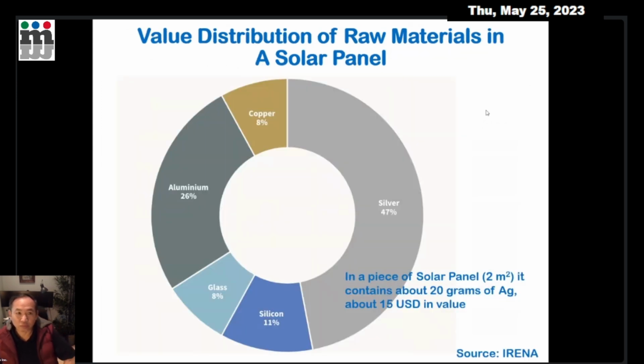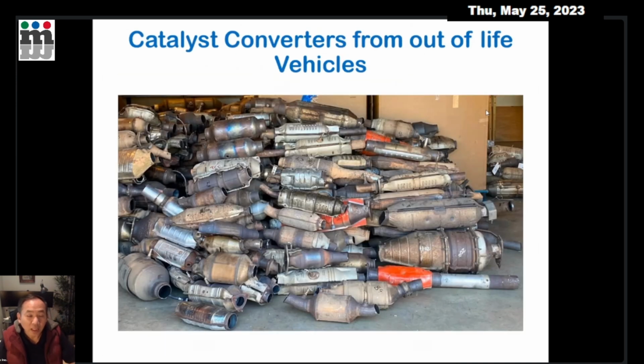And this is the value distribution in the solar panel. You can see silver is dominant, accounting for almost half of the value of one solar panel. So it's dominated by silver, followed by aluminum, silicon, and then copper.